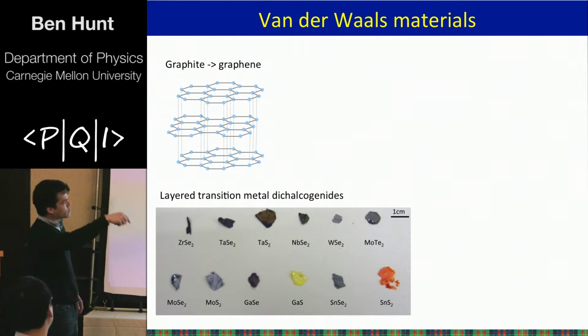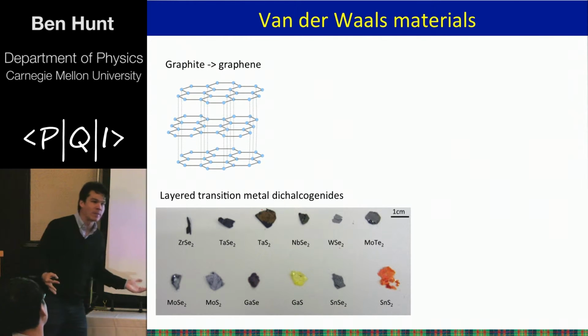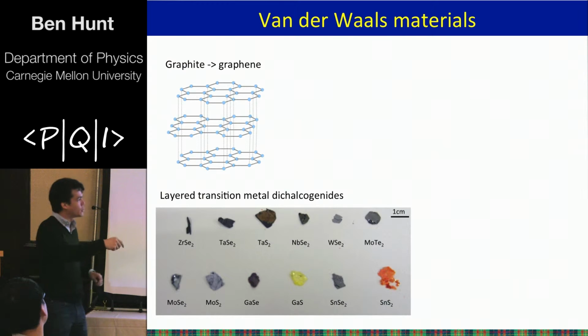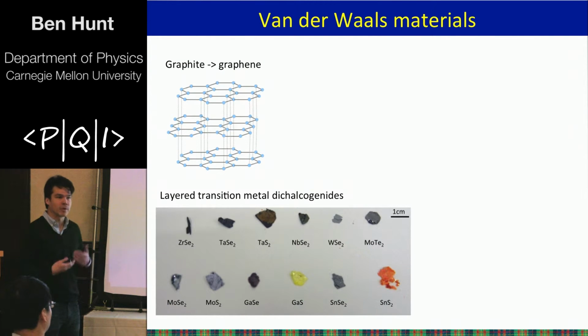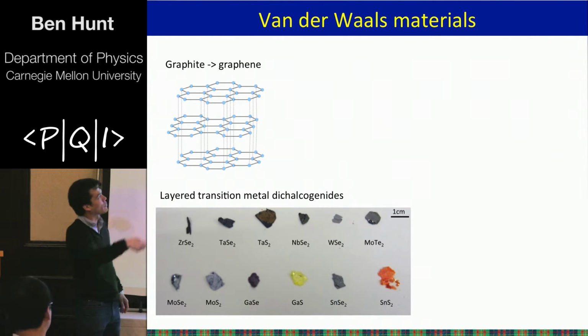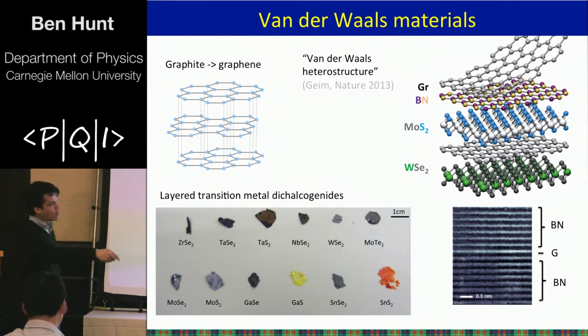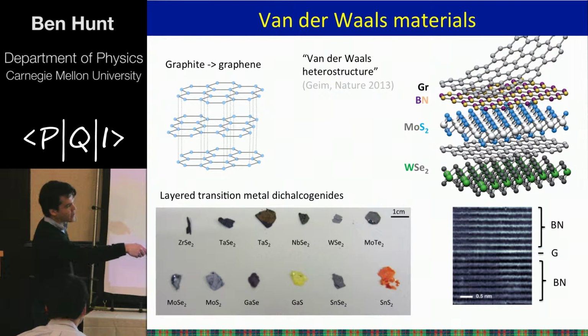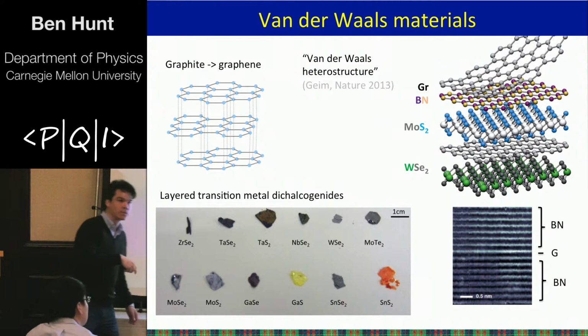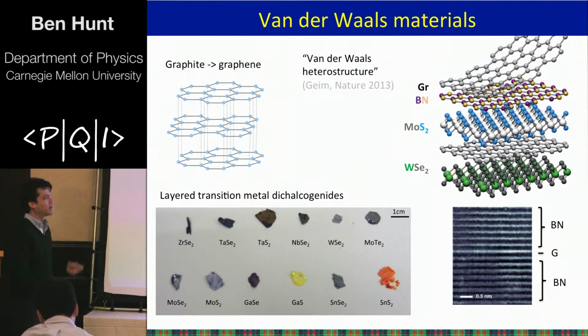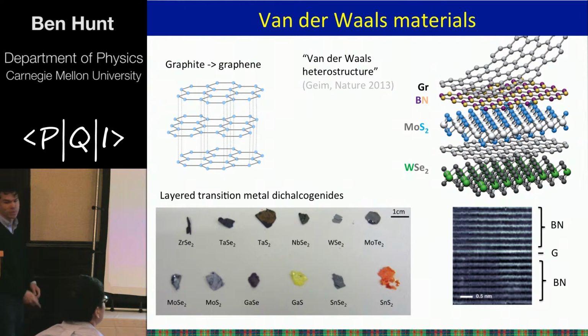And what you may not know is that there's an entire family of layered compounds that we can explore, which you can actually use also to create two-dimensional materials. And we now have techniques by which you can basically peel off layers of any superconductor or semiconductor or metal that you want, stack them up in a nice stack that Andre Geim calls a van der Waals heterostructure. And remarkably, we can make interfaces that are atomically flat and clean. So it goes from kind of a Friday afternoon type activity to being able to do some pretty serious research with these van der Waals heterostructures.